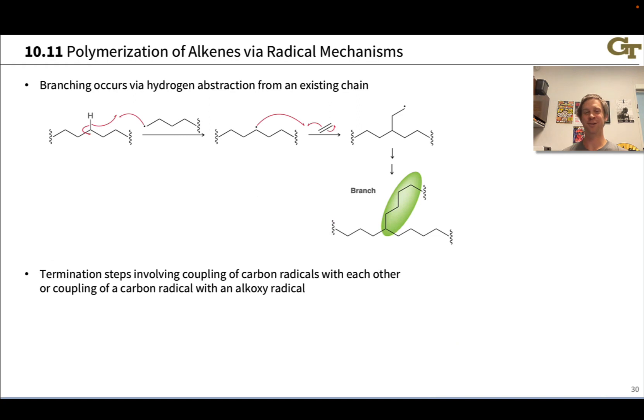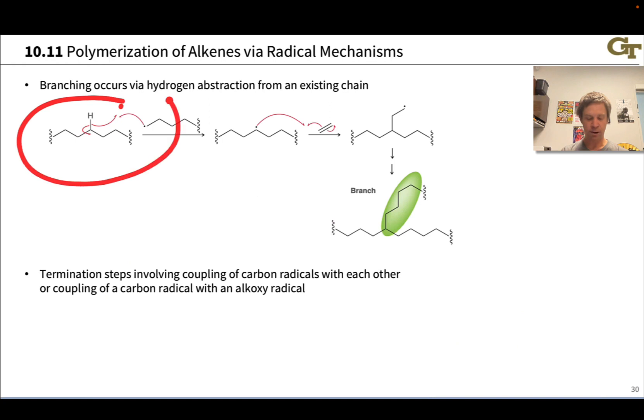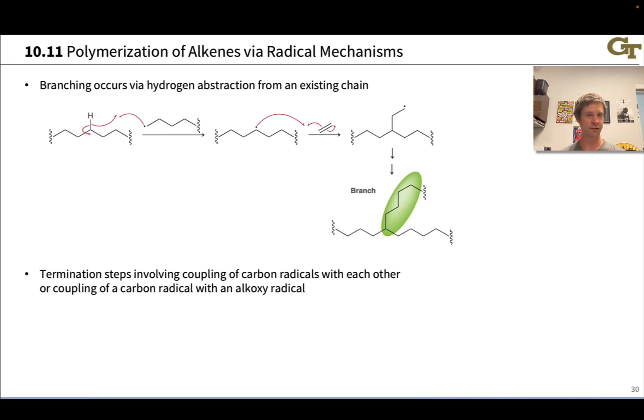When steps other than radical addition to the pi bond occur in radical polymerizations, interesting things happen. For example, the abstraction of a hydrogen inside a polymer chain can cause branching, since it introduces a radical inside an existing, further-polymerized chain. If a growing polymer chain with a radical on the end abstracts a hydrogen from somewhere in the middle of an existing chain, that original chain becomes a fully even-electron, stable chain, but a radical is now internal to the existing polymer chain — and that can polymerize, creating a branch. We can control the extent of branching by adjusting concentration, temperature, or the amount of initiator.